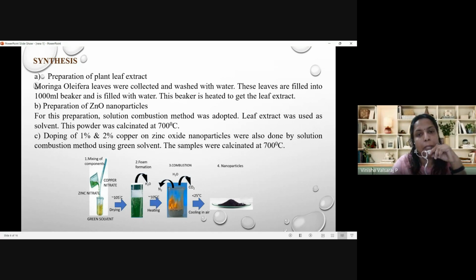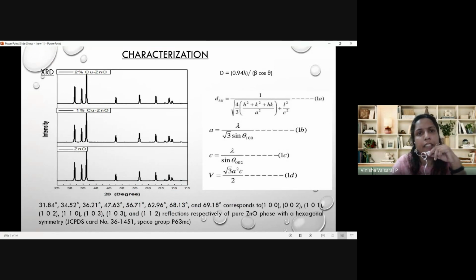The third step is the copper doping. 1 weight percent and 2 weight percent copper is doped into the nanoparticles, and that is also calcined at 700 degrees Celsius. This is the schematic representation of the procedure. And we did several characterizations.